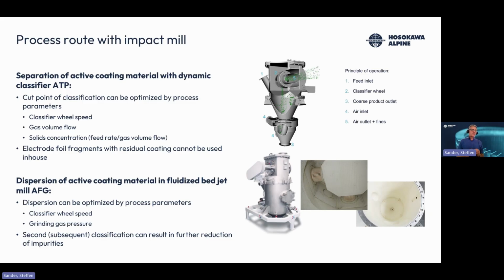And for the finer particles, the circumferential speed, or the force acting to the outwards, is lower than the drag force by the gas volume flow. So the fine particles are sucked through the classifier wheel, and the coarse particles are deflected by the wheel. So you have a separation between fine and coarse. And the fine material, that's actually the coating material that has to be recycled.